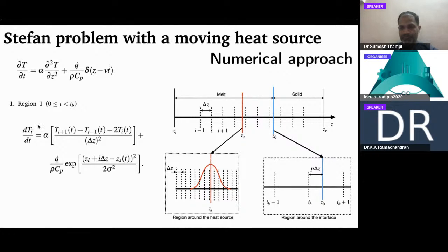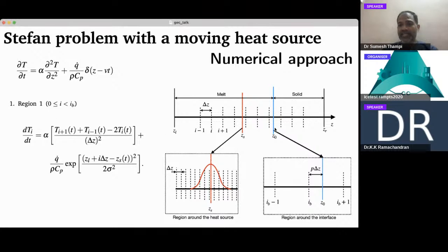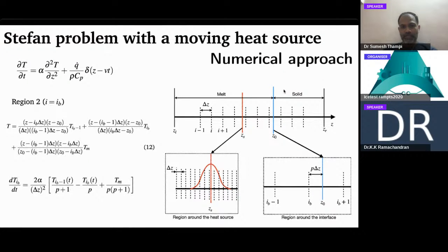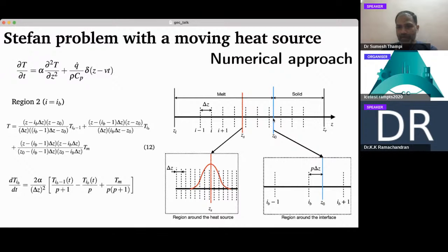And that's what we do, except that there is one catch, and the catch is that there is also an interface. At that interface this unsteady equation is not valid because there is a latent heat associated with the phase transition there, and therefore you need to account for that. The way to account for that is to use the Stefan boundary condition as I was telling you earlier. So we say that I have this interface, which is zoomed into this region here. I have the interface and a few grid points around it. I will do an interpolation technique here, to tell me what the temperature is around this point. The reason I want to do it is because I know the temperature exactly on this blue line. That has to be the phase transition temperature, or the melting point in this case.